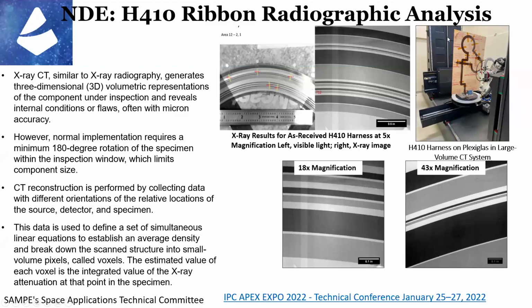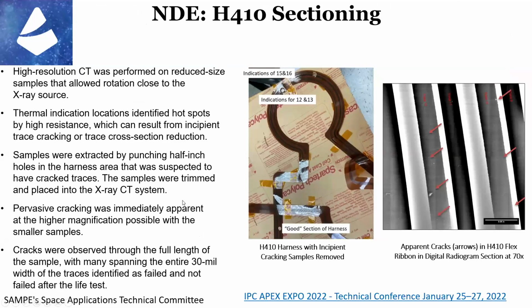So we laid out the harness full flat and started to work through it. And what we ended up finding, and it may be hard to see through the screen, is lots of little incipient cracks on the different traces, but they weren't in the thicker traces, which was a lot of interest to a lot of the people that were working this problem. We went in and cut out these small samples based on the IR signatures, and that's how we were able to get down and actually find these incipient cracks in the wiring harness.